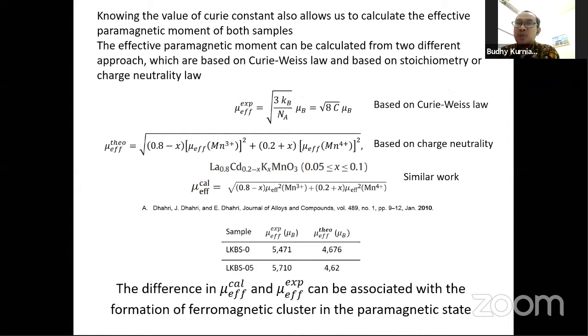And then we also try to calculate the magnetic moment of the sample, as shown in the table. We have differences in the value between the experimental and theoretical calculation. It can be associated with the formation of ferromagnetic clusters in the paramagnetic state, as we can get from the Curie-Weiss temperature, theta. Next, please.